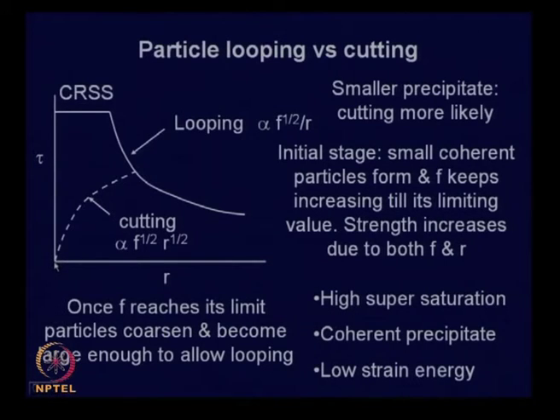See, initially you do not have any precipitate. As the precipitate grows, the volume fraction of precipitate increases, and the precipitate also grows in size, R also increases, and the stress required to cut a fine precipitate is given by the volume fraction of precipitate raised to the power half and the radius of the precipitate raised to the power half. So, this plot looks like this. This is the optimum strength that you expect. After that, if the precipitate coarsens, then the strength drops.